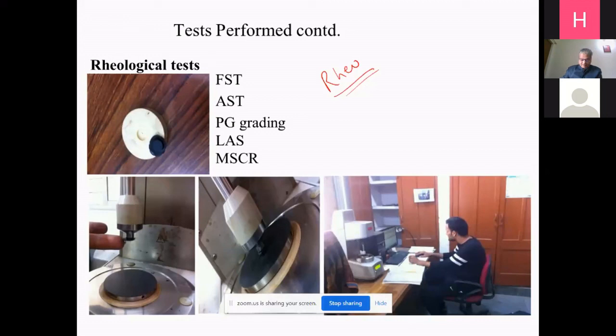So nowadays we have this rheometer. This can be used for this purpose, and it has two plates, and a drop of bitumen is placed between them, and the effects of various actions on these drops are taken. So this is the frequency sweep test, amplitude sweep test, PG grading. Nowadays PG grading is coming out, like if I say PG 64 minus 22, this means your bitumen can work up to 64 degrees centigrade on the higher side and minus 22 degrees centigrade on the lower side.